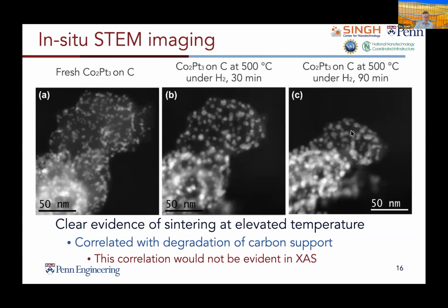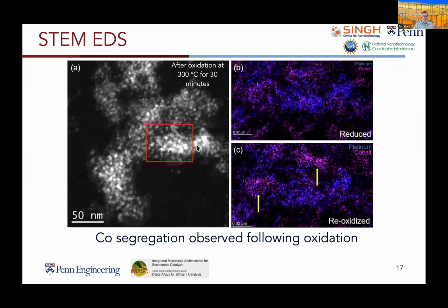If we look at this at lower levels of magnification, we can see that some of the sintering that occurs is not just from standard particle migration and Ostwald ripening, but also there's a degradation of the support. In this case, it's a carbon support. And as the support degrades, you begin to see particles come closer to each other. Again, that's something that can lead to sintering. And this is the sort of thing that would not be evident by just using the X-ray absorption. You would not have any knowledge as to the origin of changes in particle size.